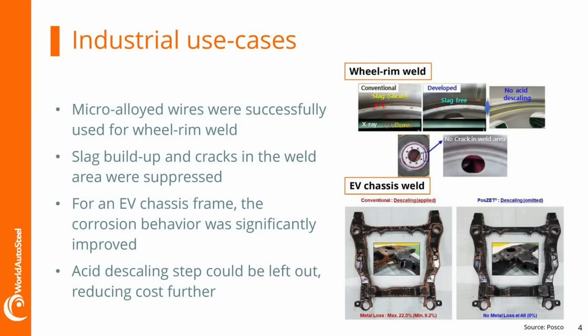A similar example is for an EV chassis frame on the bottom. The corrosion behavior was significantly improved in, again, the same 15-year accelerated corrosion test. And we also could leave out the acid descaling process, so saving us a whole process step that we would otherwise need to clean the welds.